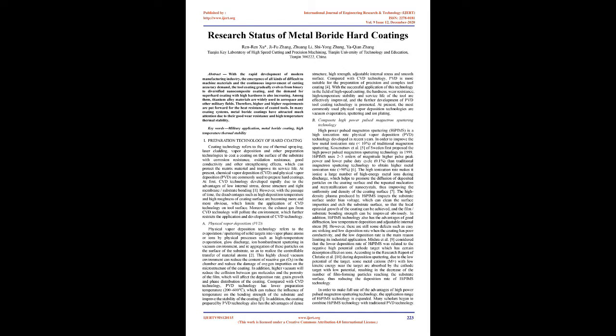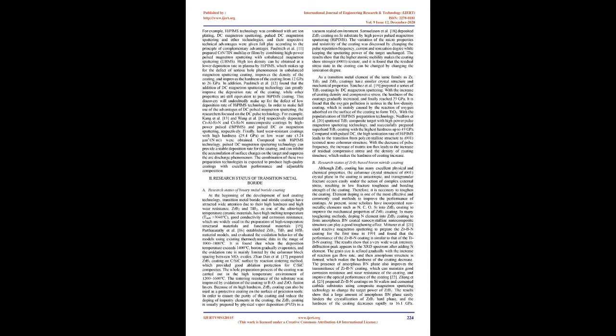HIPIMS uses 2-3 orders of magnitude higher pulse peak power and lower pulse duty cycle, 0.1%, than traditional magnetron sputtering technology to obtain higher metal ionization rate, 50%. The high ionization rate makes it ionize a large number of high-energy metal ions during discharge, which helps to promote the diffusion of deposited particles on the coating surface and the repeated nucleation and recrystallization of nanocrystals, thus improving the uniformity and density of the coating surface.